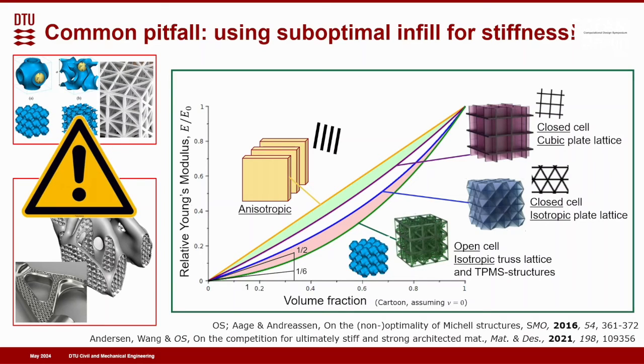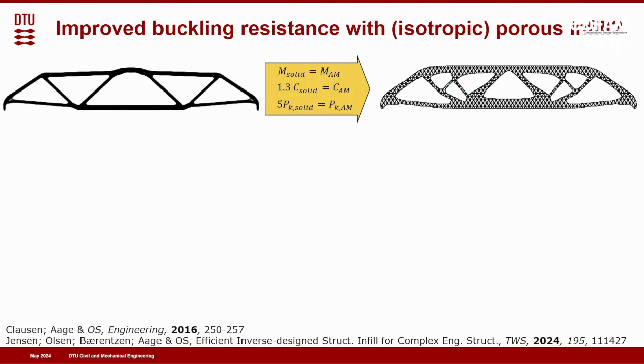One place where it might be advantageous to have microstructure is if you also think about stability or buckling of your structures. These two pictures show, to the left, a standard beam optimized with standard topology optimization, which is solid. To the right, we have a structure where we also optimized but insisted on having a fixed volume fraction of triangular isotropic microstructure. They have the same mass, but as I just said, the one to the right has suboptimal microstructure, which means the compliance is 30% worse. It's 30% less stiff. So maybe we can tolerate that in this case because it turns out that the buckling stability, the ultimate load it can carry, is actually 5 times higher than the solid structure.